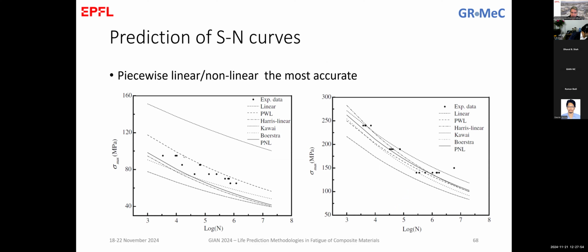In the first case, we see that, as expected, the linear diagram is very inaccurate. It actually overestimates the material performance for all the cases. The other diagrams are more or less the same, good, except in this case the Harris diagram, when we use the linear interpolation, that is very, very low. In another material system, I think this is the 15, this is the on-axis case. Again, we can see most of the diagrams are quite good, with the piecewise linear and non-linear in all cases being the best ones in these comparisons.